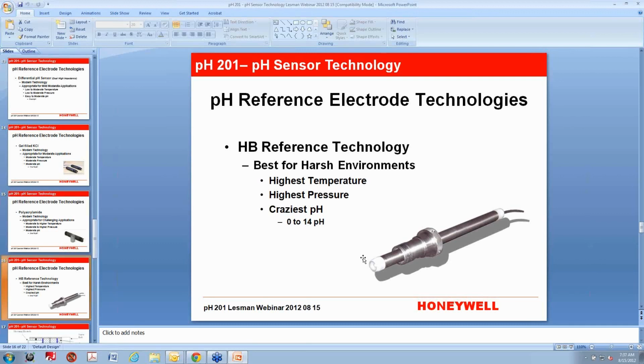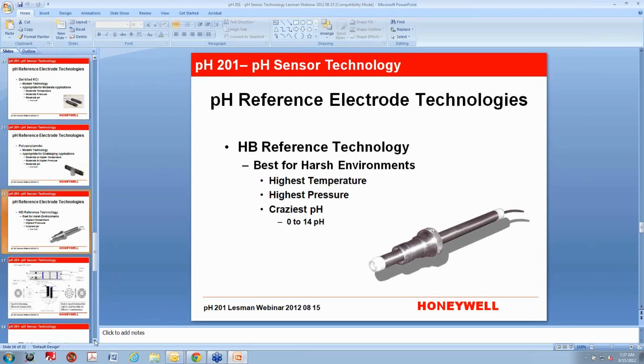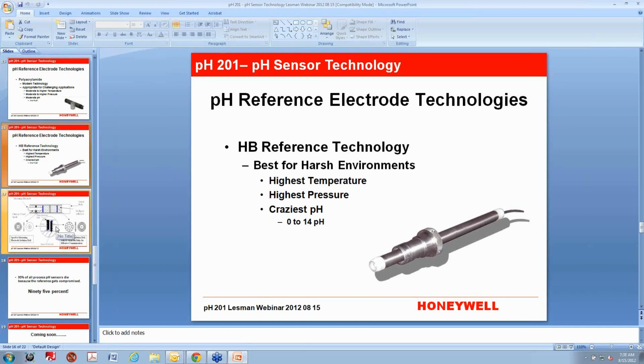If you put it into what's called a pressure monster body, which is a stainless steel or Hastelloy or titanium body that threads into the process, it's not ball valve insertion. I did an application for a downhole oil application, and we rated it to 5,000 PSI. And there's not a pH sensor on the market that goes that high. That's really crazy. It'll easily go 0 to 14 pH. Now, the farther away from 7 you get with any pH sensor, the shorter its life is going to be. But when you get into nasty environments, this particular reference technology is going to have the longest comparative life to, say, a gel technology, the polyacrylamide, all of those other ones that we talked about.